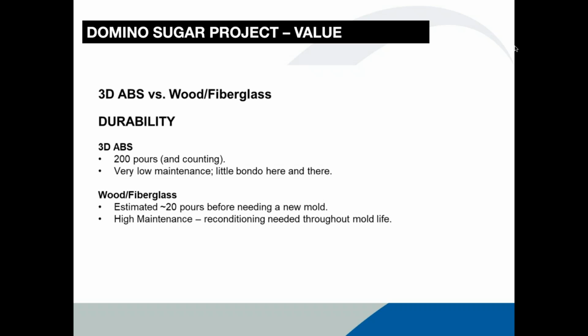Now, with a wood fiberglass form, you cut your plywood, assemble it all together, caulk your joints, and fiberglass over resin, all of that. From my understanding, it can be upwards of around 20 pours before you might need to scrap that mold and make a new one. And in between each pour, you're doing a lot of reconditioning, fixing and repairing. So they're more high maintenance than the 3D printed ABS.